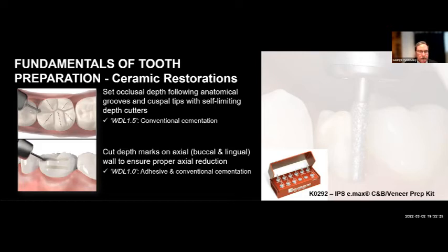Typically, we reduce about 1.5 on the occlusal for a posterior restoration with glass ceramics. With 3Y, we're down to about 0.6 minimal. It's not a goal to cut a prep at 0.6. I'm just saying you can get away with 0.6, but if you can do 0.8 to a millimeter, that certainly allows for a better, stronger restoration overall.